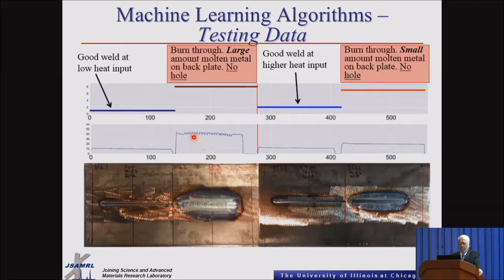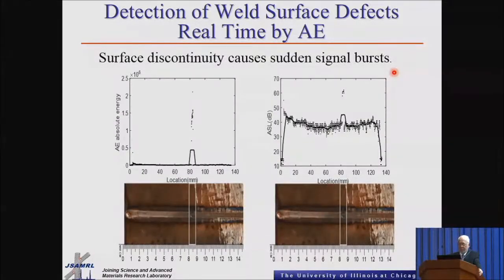As you increase the heat input, you can see now that you have some type of burn through, but there was no hole, so there was some amount of metal on the back of the plate. We repeat it again with a second weld, changing the heat input. Again, for the high heat input on the right-hand side here, you can see there was no hole being formed. However, there was some of the metal that accumulated on the back of the plate, which again could be either burn through or could be the onset of burn through.